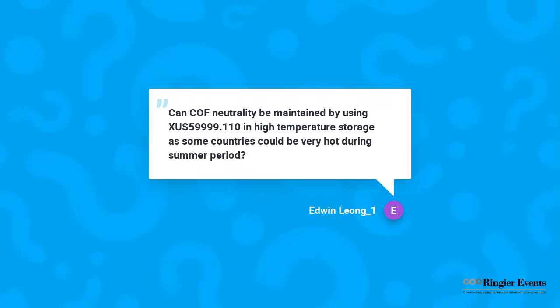Can COF neutrality be maintained by using XUS 59999.110 in high temperature storage, as some countries could be very hot during the summer period? In our laboratory evaluation, we have found that for the storage, I think in one of the slides we did show some data, with our XUS 0.110 the COF can be maintained to be more stable, more neutral compared to the traditional metallocene PE resin. So if you have a situation where you need to store materials at high temperatures, such as during summer, this resin could help.